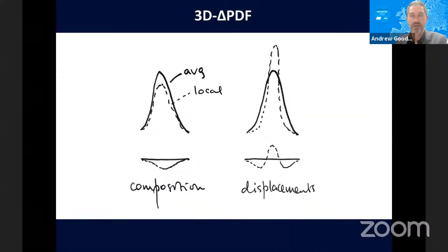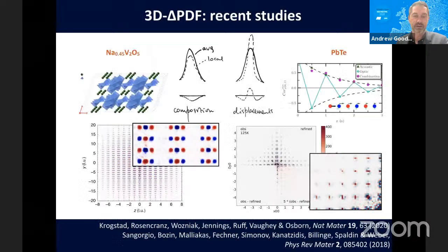Now, I'm mindful of time, so I will try and go through these slides quite quickly. Let me just flag why I think these are so interesting and useful for us as chemists, because what this difference pair distribution function does is allow us very easily to see the microscopic origin for the diffuse scattering that we observe experimentally. We get different signatures in these difference functions if, say, the key thing is local compositional ordering, or if it's due to correlations and displacements. And if I had a bit more time, I'd go through this, but basically if you get a feature that looks a bit like a monopole, or it looks like a quadrupole here, you can distinguish one from the other. And that's because of these differences between the average and the local pair correlations.